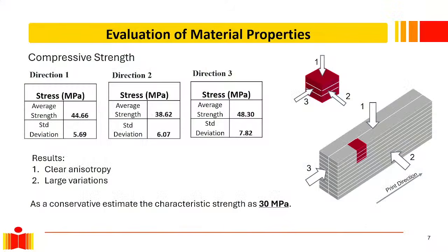Now this gets us out of our comfort zone because everything that we do with concrete design, we treat as an isotropic homogeneous material, which basically means the material is behaving the same in all directions and at all locations. That's not true here. You have layers and they're separated by interfaces, which creates anisotropy, and that is reflected in the material properties. Now, if I was to design with this, which material property do I use?